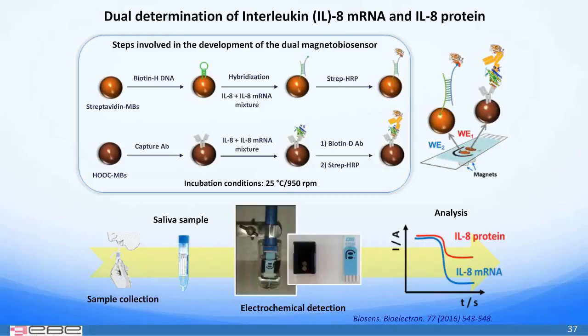The implemented methodology involves the use of magnetic beads functionalized with specific antibodies against the protein and a specific helper DNA probe for mRNA, and amperometric detection at disposable screen-printed dual carbon electrodes. In this case, the disposable electrode is placed in a homemade magnetic holding block with two encapsulated neodymium magnets to ensure the reproducible and stable magnetic capture of the modified magnetic beads onto its working electrode to perform the amperometric measurement.